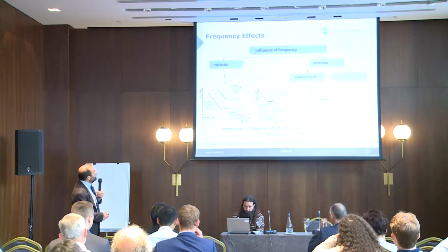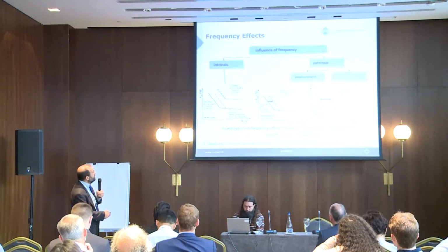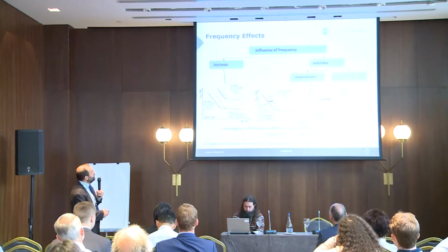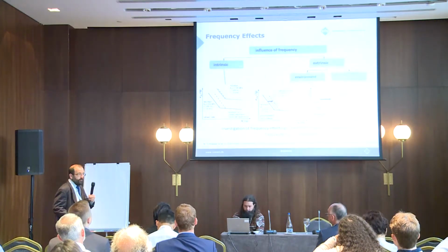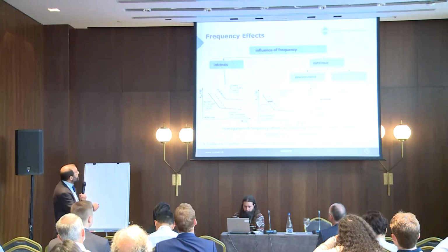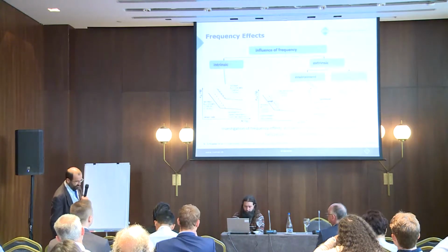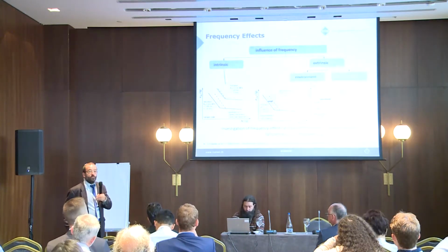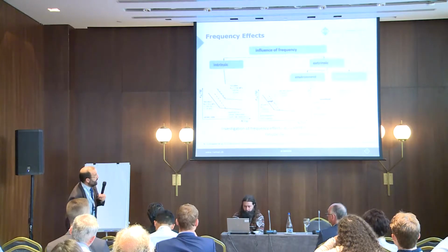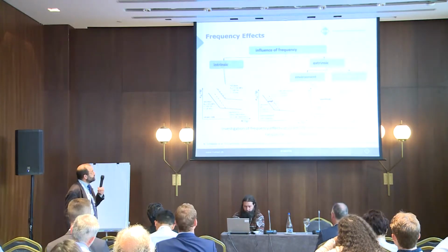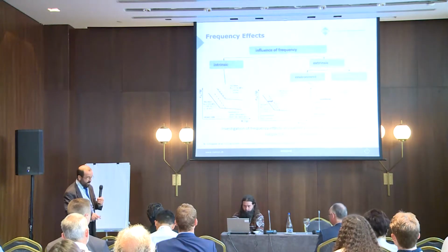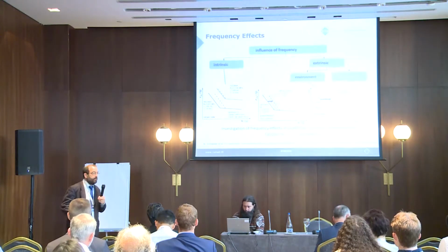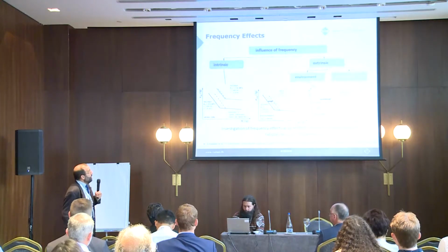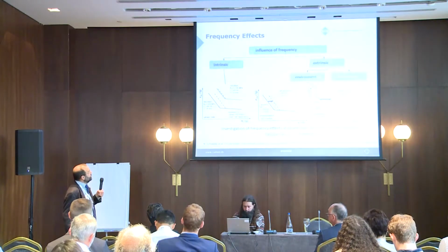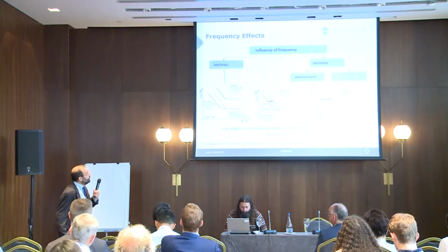A similar effect he could find when testing the same material in inert atmosphere. So he could conclude, especially that on the same material in very hard condition, he could not find a frequency effect. That this must be related to the strain rate. One also has to have in mind that the strain rate is not constant during testing. It's a sinus shape, and so it is not so easy to really understand and to make the right conclusion.